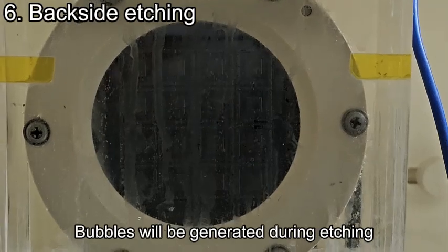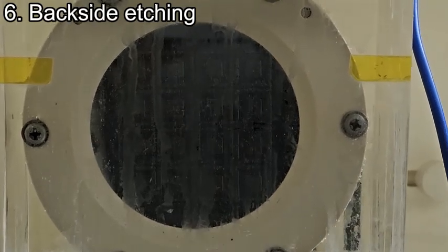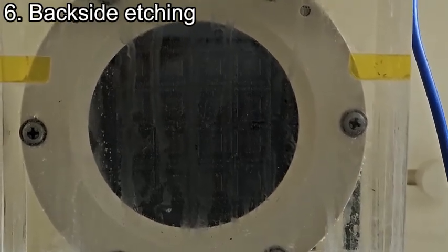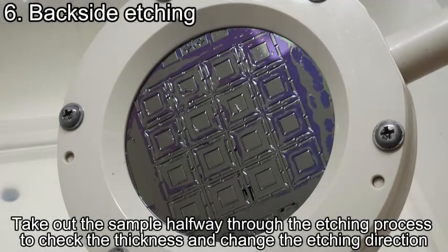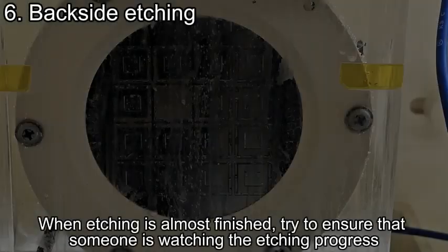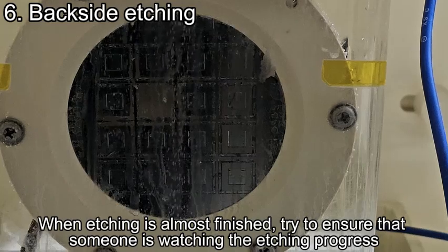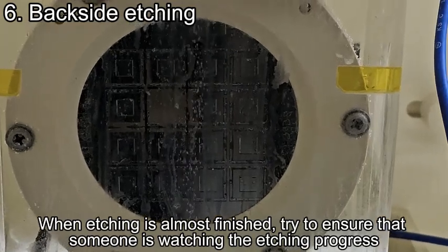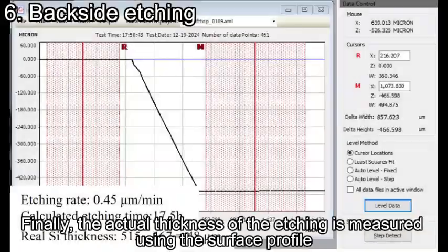Bubbles will be generated during etching. Take out the sample halfway through the etching process to check the thickness and change the etching direction. When etching is almost finished, try to ensure that someone is watching the etching progress. Finally, the actual thickness of the etching is measured using the surface profiler.